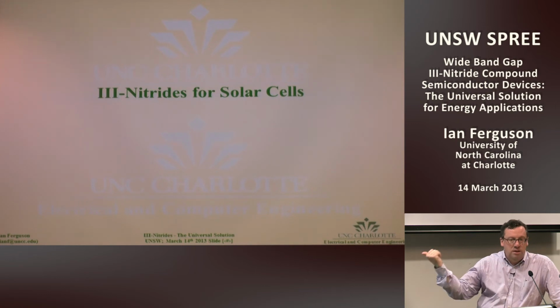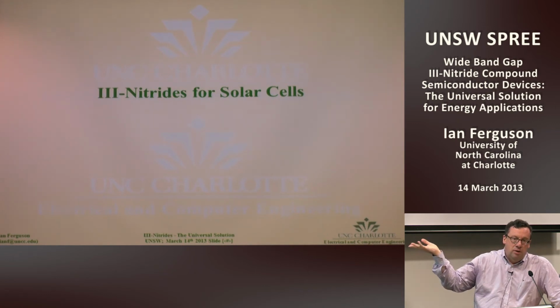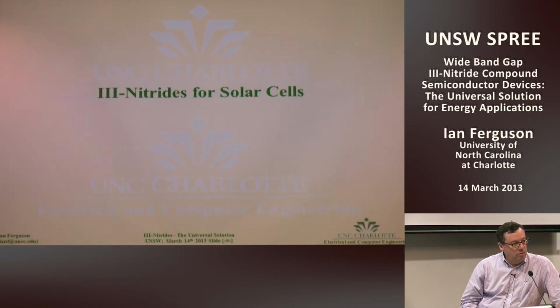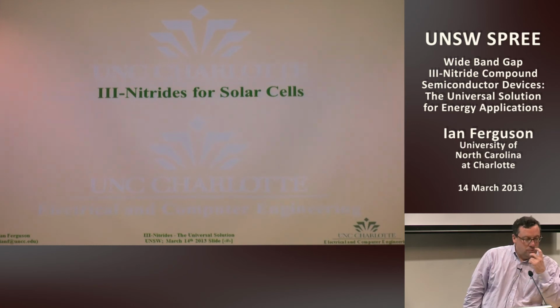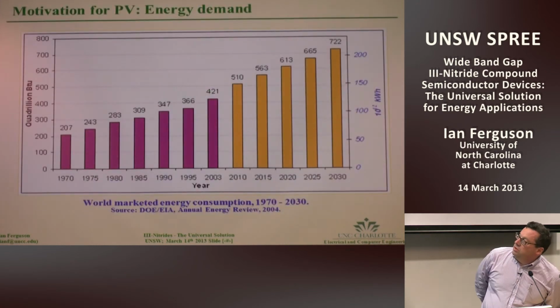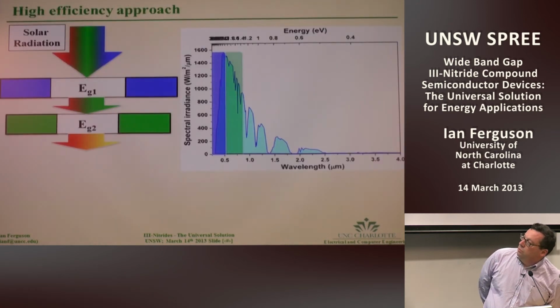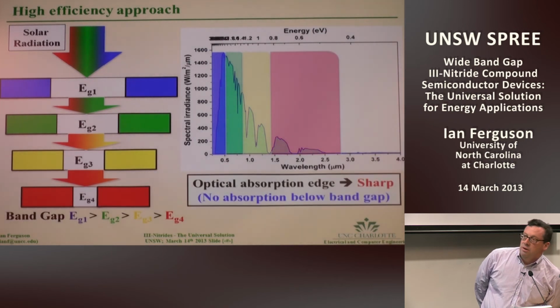Typically what you're going to see on these solar cells, the active region, the intrinsic region where you absorb, is only about 0.2 microns thick or so in these devices. So they're very thin devices. And these devices were also designed for concentration. I think the stuff we've kind of moved through, and people should probably already know this.